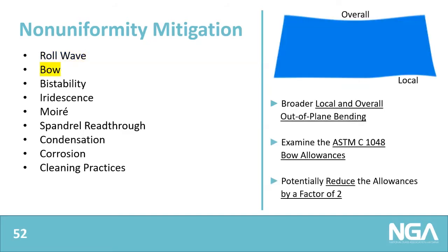Bow is a situation that involves the glass edges. As you can see on the screen, it could involve the entirety of a glass edge or a localized portion. ASTM C1048, which addresses heat strengthened and fully tempered glass, introduces allowances for bow, but those bow allowances are fairly generous, so you may want to reduce them by a factor such as 2.